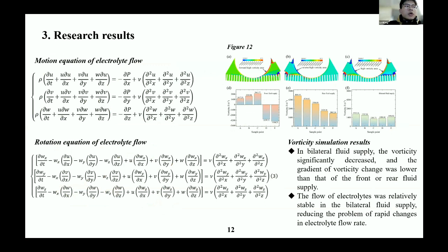After transforming the momentum equation of the electrolyte, the rotation equation of the electrolyte is obtained, as shown in this picture. And the eddy current in the processing area is further analyzed by the magnitude of vorticity. In Figure 12, the vorticity size is significantly smaller when the liquid is supplied from both sides than when it is supplied from one side, indicating that bilateral liquid supply can ensure the stability of the flow field and is beneficial for the actual processing. Therefore, in subsequent experiments, a bilateral liquid supply method was adopted.